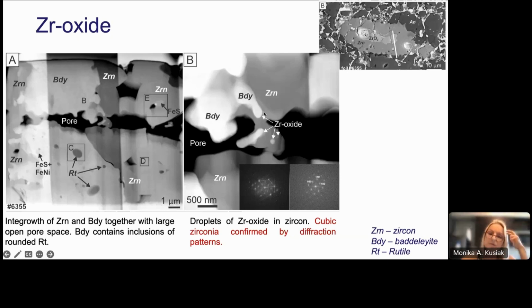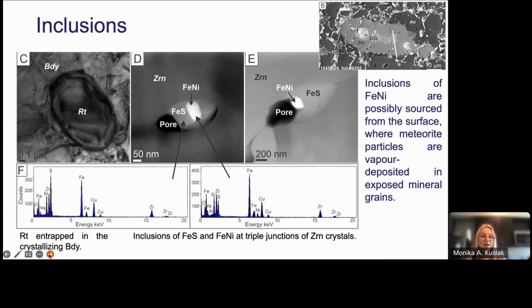However, these droplets are very nicely visible in this picture in the center. These are droplets about 20-30 nanometers in scale, so they are not huge droplets of cubic zirconium oxide. As well, there is big porosity and other inclusions in the zircon. The other inclusions are rutile, which is here on the left. This particular rutile grain is in baddeleyite, and as well we have sulfides of iron and iron-nickel, usually in the triple junction between the zircon crystals.